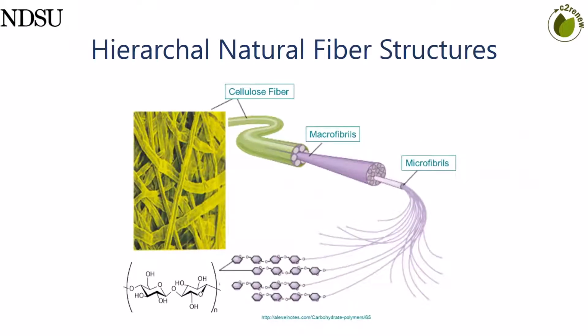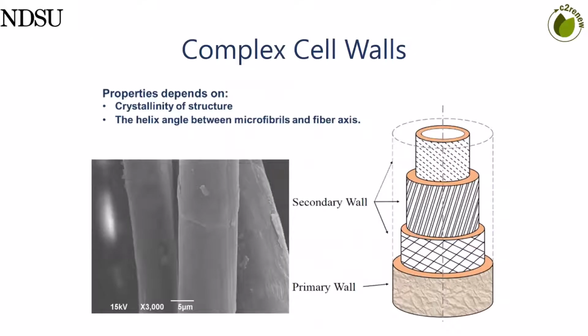A lot of the dampening and insulative properties from natural fibers stems from their hierarchical structure. They're very complex structured fibers with the cellulose as the backbone, and your pectins and your lignins adhering them all together in this multi-step fashion, as illustrated here. The strength and the stiffness of your fiber really comes from that secondary wall and how the crystalline cellulose is oriented in that secondary wall.